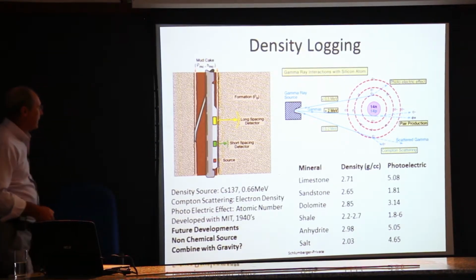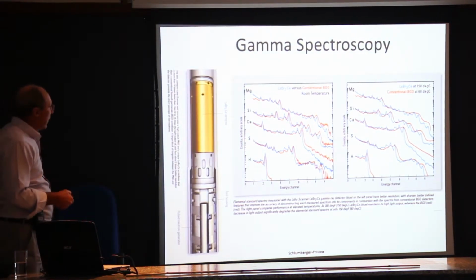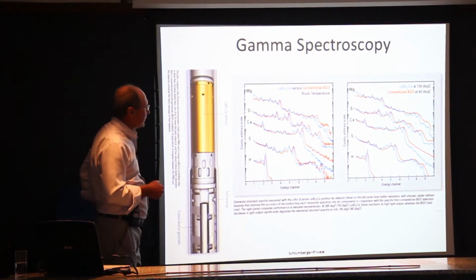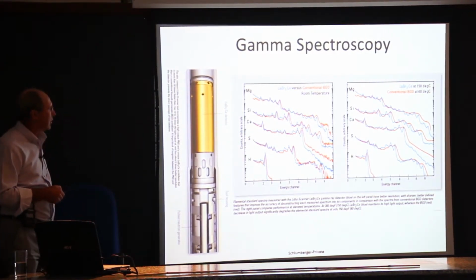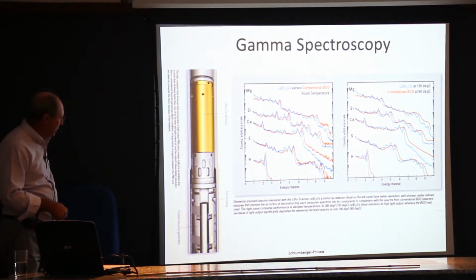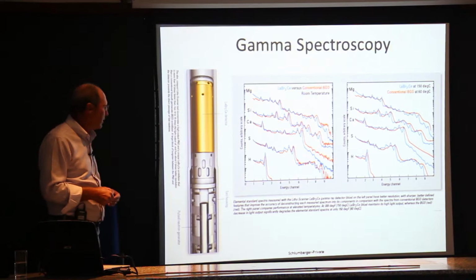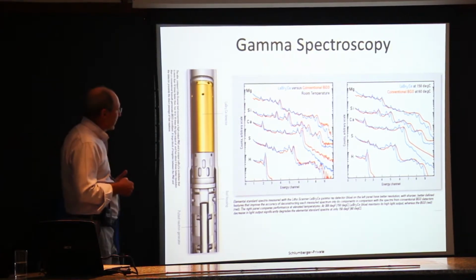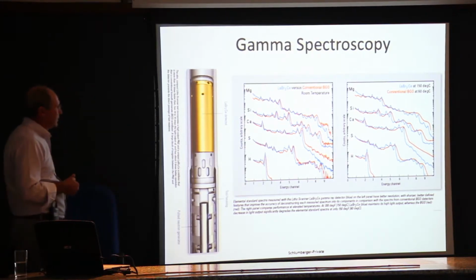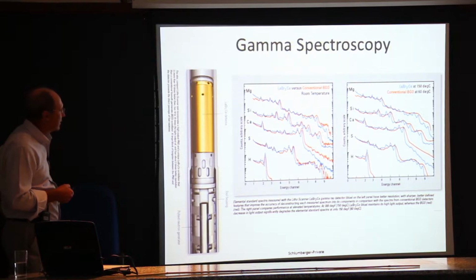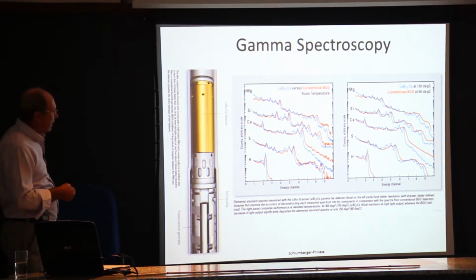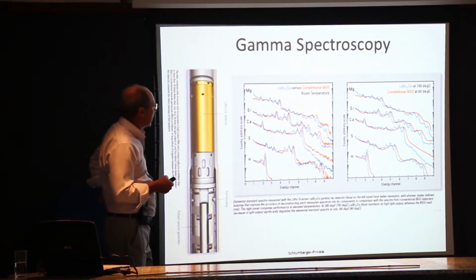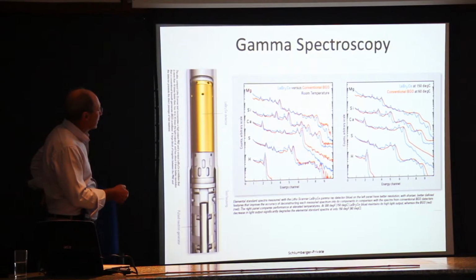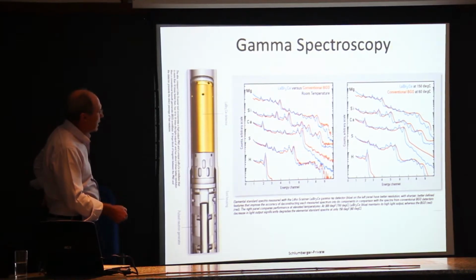I think you'll see a lot of interest in the pre-salt. Gamma spectroscopy, or nuclear spectroscopy, has been a very good development for the pre-salt. With gamma spectroscopy, we basically have a pulse neutron generator emitting very high energy neutrons, about 14 to 15 MeV. And the neutrons interact with the formation. There's both inelastic and elastic interactions. And then the gamma rays and the energy level of the gamma rays given off can be measured, and